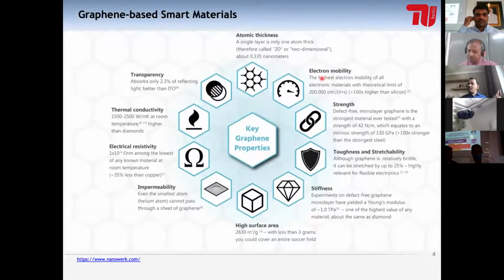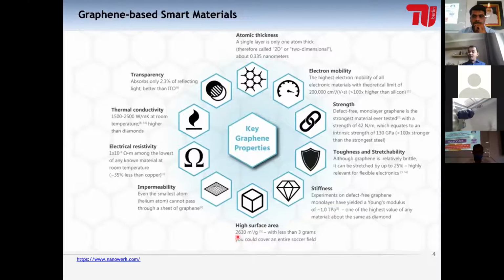They have high electron mobility, which gives their application in optoelectronics and other electronic applications, and which can be measured by normal measurement techniques. They have good strength, they are defect free, and once they are attached to each other, they have very good strength, which can be measured by normal physical methods. They are very tough, and their stretchability is high. They have very good stiffness, and most important, they have very high surface area. Some of the materials reported till now have a surface area of 2,630 meters squared per gram, and this is going into even higher values.